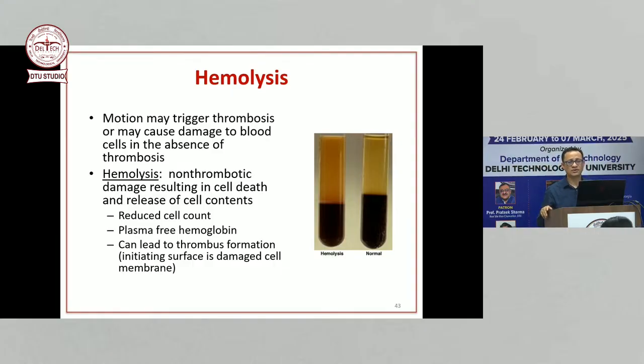Another thing, when we work with blood, you have to work with blood very, very gently. You cannot just take a blood vacutainer or something and shake it, because by doing all this, you are really activating the platelets. Even when I'm drawing blood and transferring it to another container, you are not just dropping the blood, you gently put the blood so it slides down rather than just drop, because dropping the blood you might be activating the platelets. So you have to work with blood very, very gently.